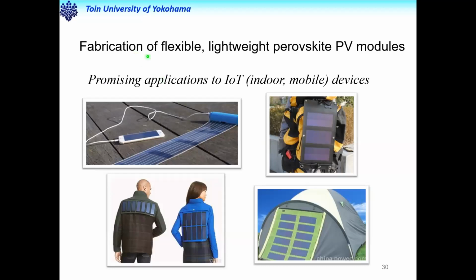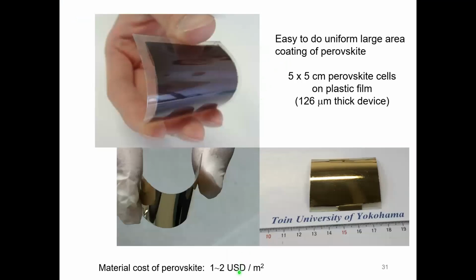One is making super lightweight and flexible perovskite solar cells having a very high energy density. So you can imagine this kind of application, especially the promising application in the IoT industry, indoor and mobile applications. We also fabricated such a flexible solar cell coated with perovskite from solution, and the total thickness of the device was 126 micron, very, very thin. Still, the cost of perovskite material is $1 or $2 per square meter. This is the cost of just the perovskite, without the substrate and other materials.